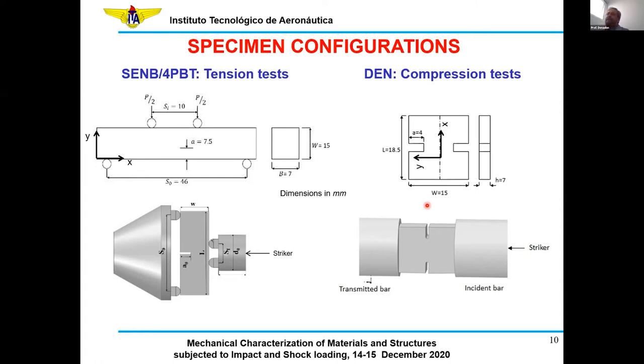Furthermore, they have a suitable layout in order to ensure that we excite the desirable failure mode. And moreover, they also must fit in a split Hopkinson pressure bar, because the idea here is not to characterize only the quasi-static properties, but also the properties at very high strain rates.